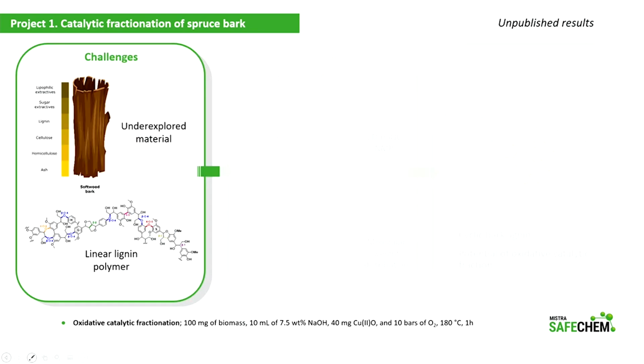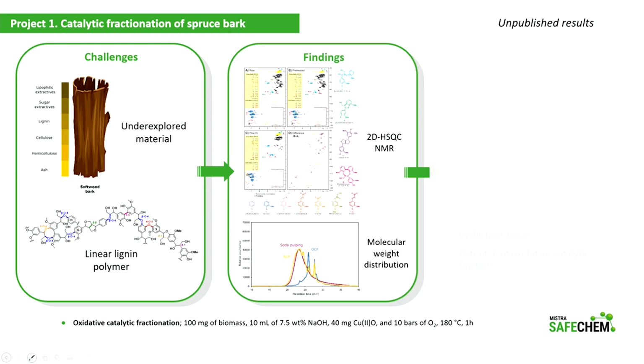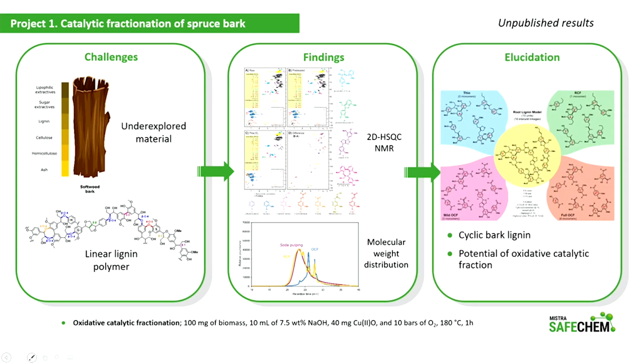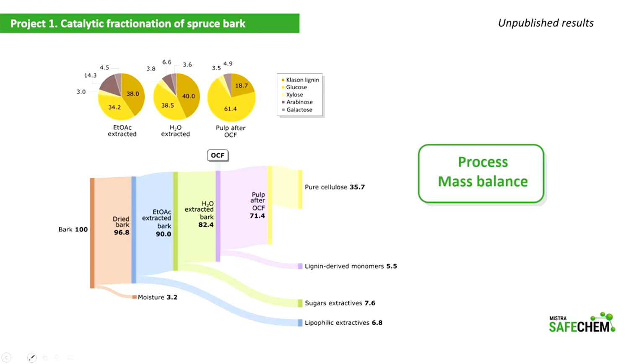Bark is underexplored and less understood compared to wood, with limited knowledge about its lignin, typically assumed to be linear. We achieve a high yield of lignin monophenols, notably vanillin, from bark. Using 2D NMR, we explore the lignin structure and obtain valuable insights. Our analysis suggests that lignin in bark is cyclic, aligning with our findings. We demonstrated the effectiveness of oxidative catalytic fractionation, OCF, in upgrading cellulose to nanocellulose and depolymerizing lignin to high-yield monophenols. We also showcase the mass balance of our process to ensure minimal loss and optimal resource utilization.